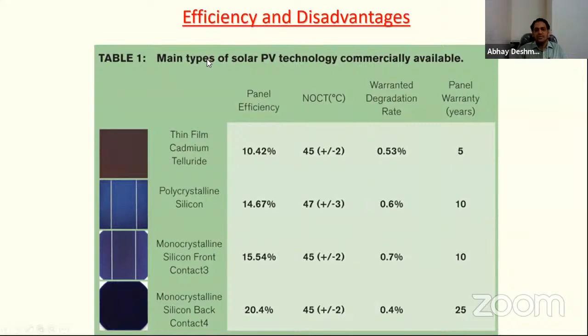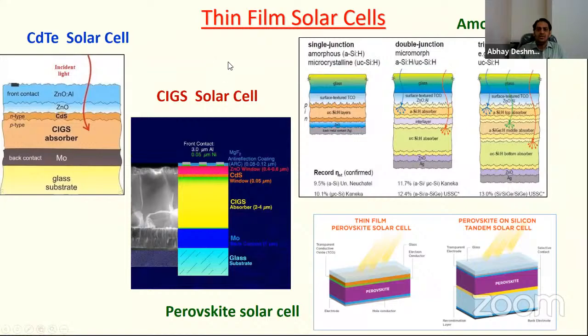So, these are some thin film solar cell technologies, and this is a structure of that. You have a CIGS absorber, then back contacts are molybdenum, then you have glass substrate, and then CdS, ZnO, and other kinds of layers. And this is your CIGS solar cell structure, and this is an amorphous silicon solar cell. This is your single junction cell. Then you have a double junction cell, triple junction cell, and you can stack four. We have reached 4 junction cells till now.